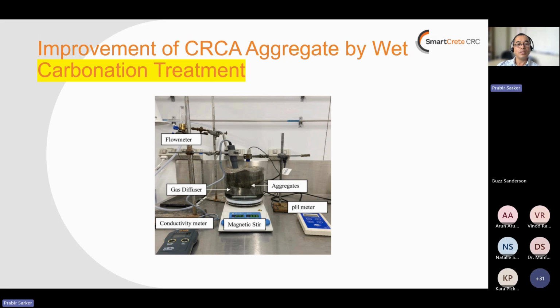So Ojoy made this setup in the lab. It is a very small scale, but later he actually did make another setup which can treat a larger volume of aggregate. So this was the preliminary setup to see the effect of carbonation on the recycled aggregate at a very small scale, but then that was increased to a larger setup which could treat maybe 30-40 kg of recycled aggregate.